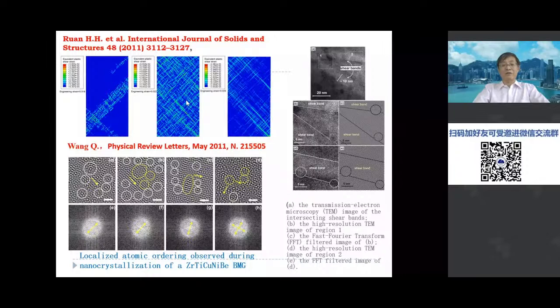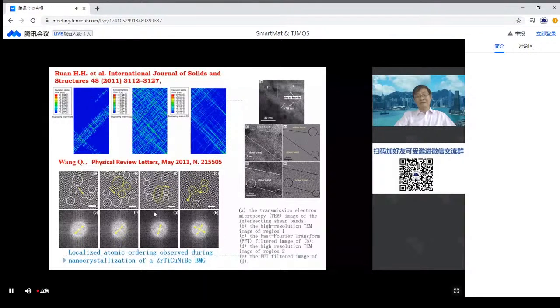So in 2011, we have done some simulation work. We demonstrate if we are able to generate a material with two phases with a difference of 20% of mechanical property, then it's possible, mixed at atomic level, to generate a multiple shear band structure that may absorb the energy to generate a higher deformation capacity. Then we tried to obtain this with a heat treatment, and we can obtain some area with order and some other area without order, like this structure, but it's not homogeneously distributed in the structure. So the overall behavior is like metallic glass. So for this reason, we continue to search how to generate a multiple phase material.